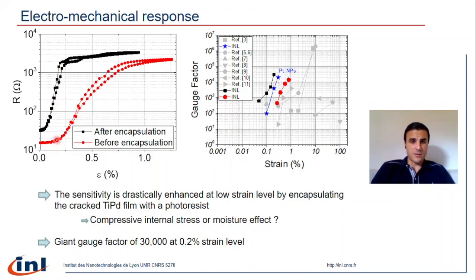More importantly, you can see that we can drastically enhance the sensitivity at low strain levels by encapsulating the cracks with a photoresist. We believe that this increase in sensitivity is possibly due to compressive internal stress within the photoresist, which shifts the sensitivity curve to the low strain level, or also to the effect of moisture on the resistance of the crack. We will discuss this more in detail in the next slide.